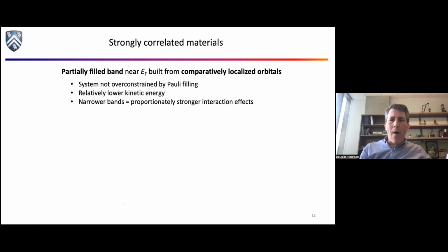So when does this fall apart? Well, the answer seems to be, if you want to get strong correlations, strong interactions, you want a partially filled band from comparatively localized orbitals. Okay, so like d and f orbitals. And so what you find is that the energy bands, the kinetic energy, doesn't vary very much with momentum. And if the kinetic energy is small, then you don't need much interaction to dominate the kinetic energy part.